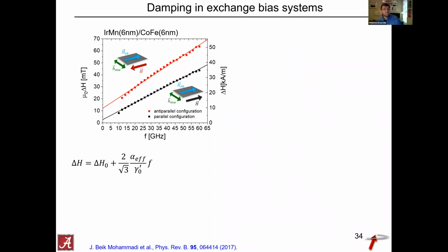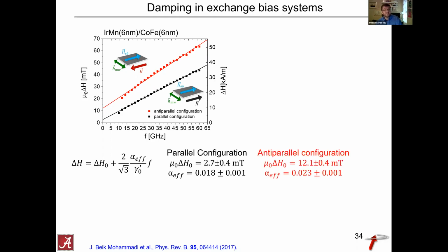And that's shown here, again, in these two configurations where you apply the field parallel to the bias direction and anti-parallel. And you can clearly see that these two dependencies are clearly different. And if you want, you can try and fit this with a straight line and extract something that I would call the effective damping parameter. And you obviously then see that in the parallel configuration, you get a smaller damping parameter than in the anti-parallel configuration.